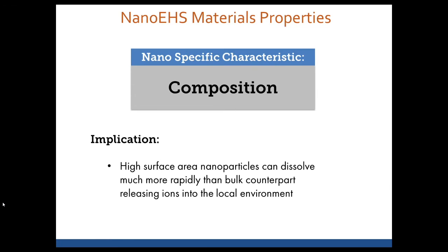The other things that we can look at are composition. I had mentioned earlier that silver was relatively dynamic. It has a dissolution constant in water, and over time it can release ions. And in the case of silver or copper, those ions are toxic. So it's not necessarily that the nanoparticles themselves have a very high toxicity, but it could be that the ions they're releasing in that local environment do impact the toxicity or the effect of them on the environmental biological system that's around them.